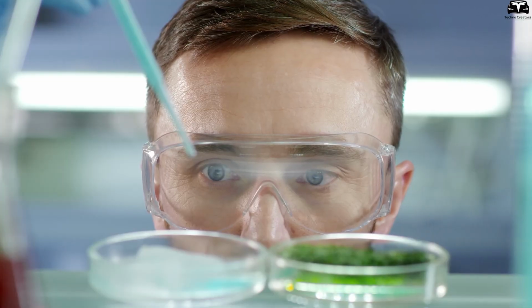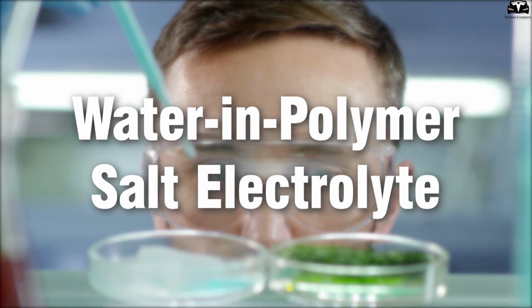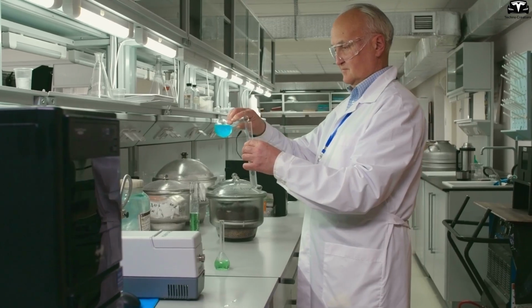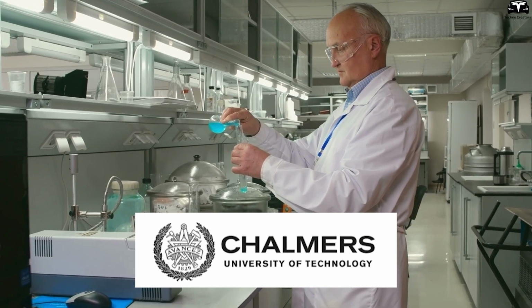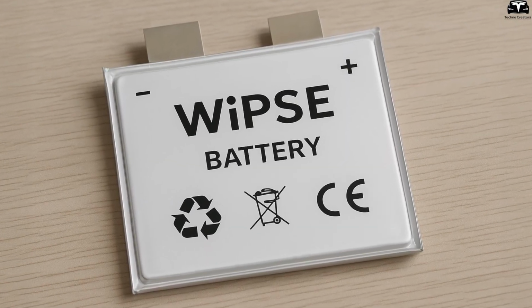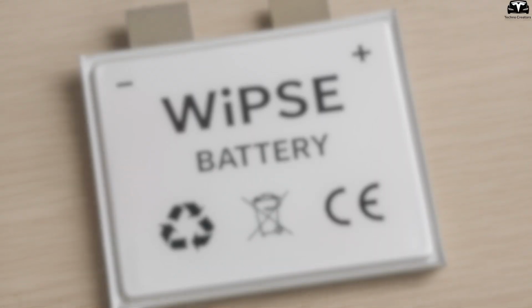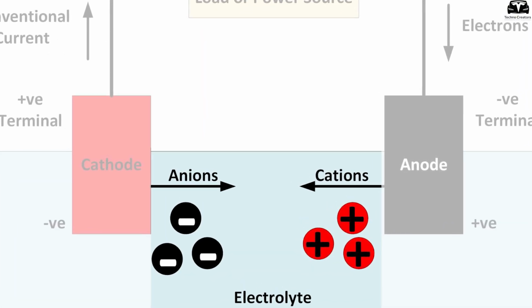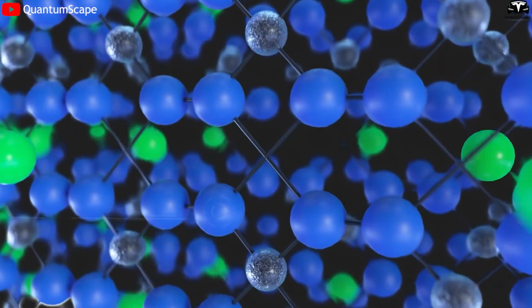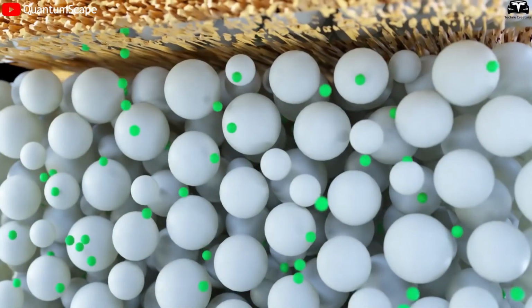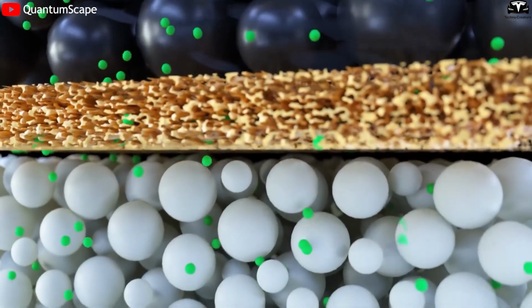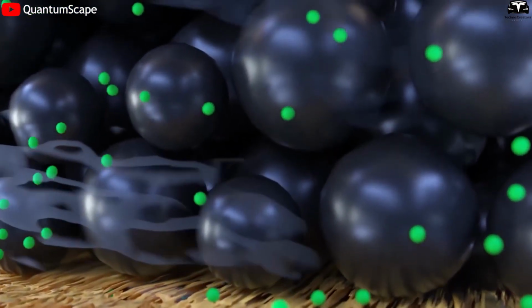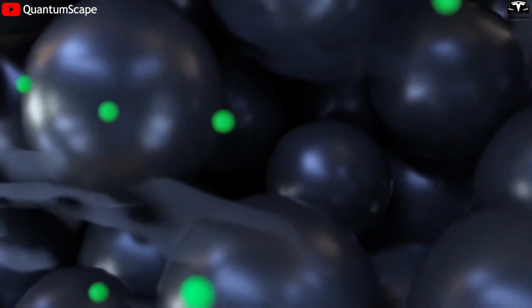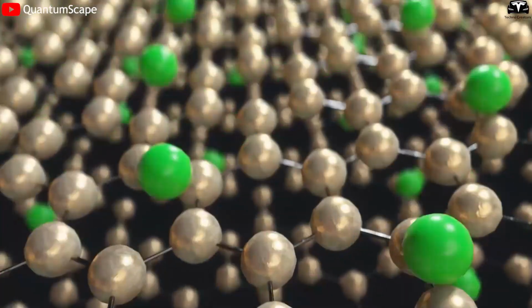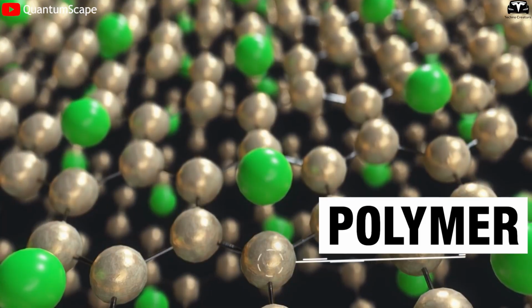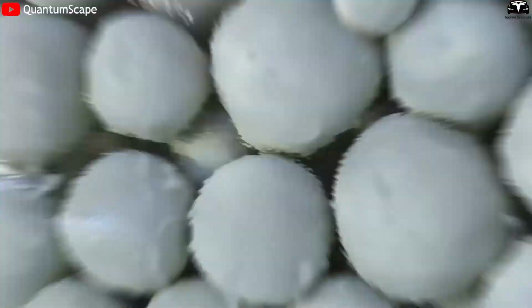However, a breakthrough came with the invention of a new electrolyte called Water-in-polymer salt electrolyte, developed by a research team at Chalmers University of Technology, Sweden. The uniqueness of WiPSE lies in its chemical mechanism and material structure. Instead of allowing free water to exist in the electrolyte solution, the researchers used a supramolecular polymer network to trap water molecules in hydration cages. There, salt ions at very high concentrations, the molar ratio of salt to water far exceeds that of conventional solutions, are organized within a porous polymer structure, minimizing free water diffusion and thereby significantly reducing charge leakage currents.